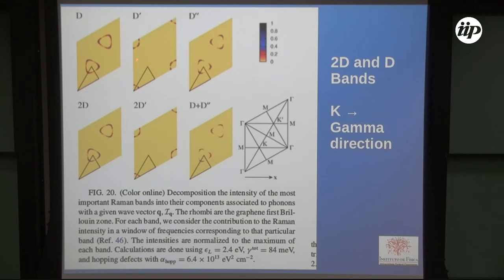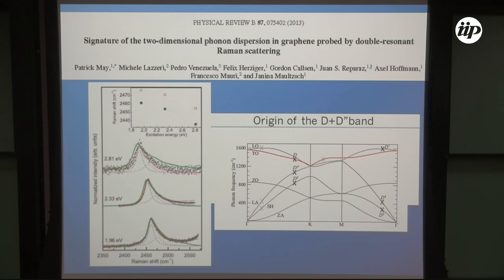Here, I plot the Raman intensity, but usually we plot Raman intensity as a function of Raman shift, the frequency, basically. But here I plot Raman intensity as a function of the wave vector. Because it's a two-dimensional material, we have these nice maps that show us in each direction where the bands will appear. So this is very useful to understand better the experimental problem.